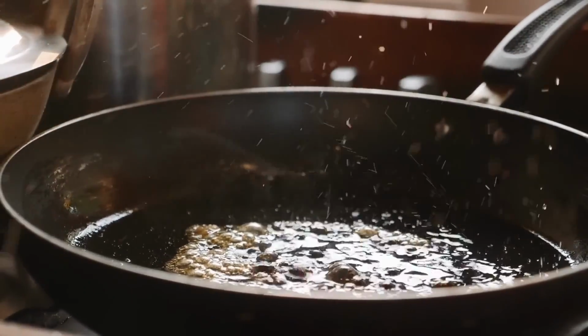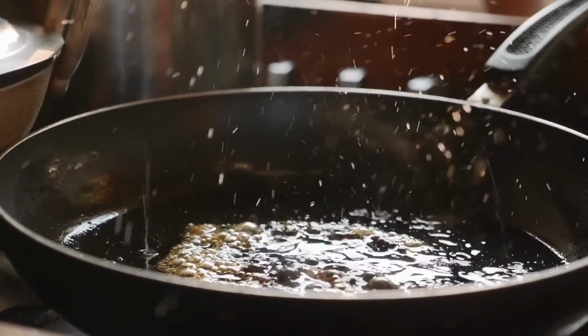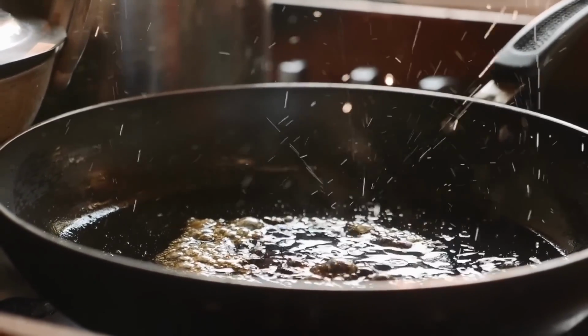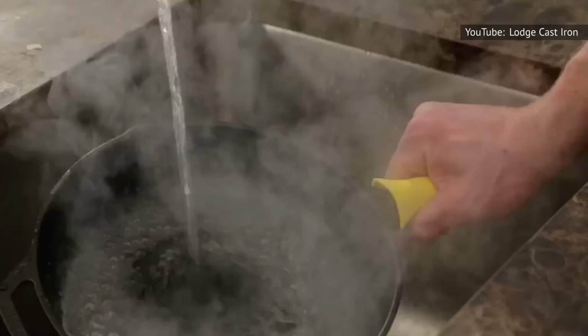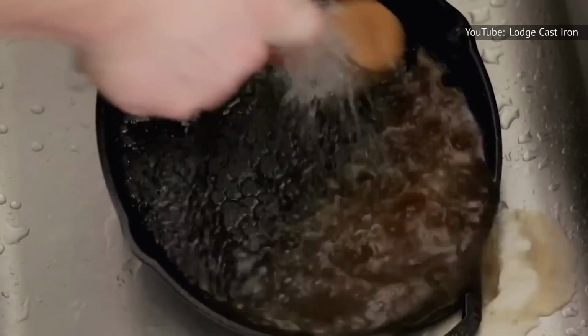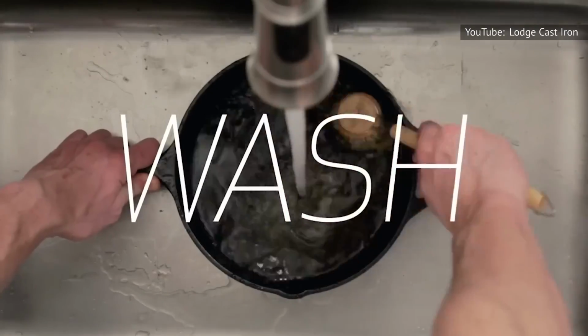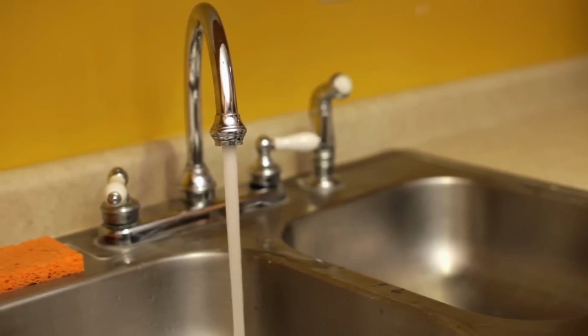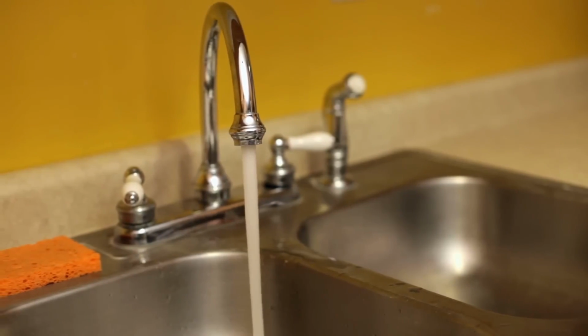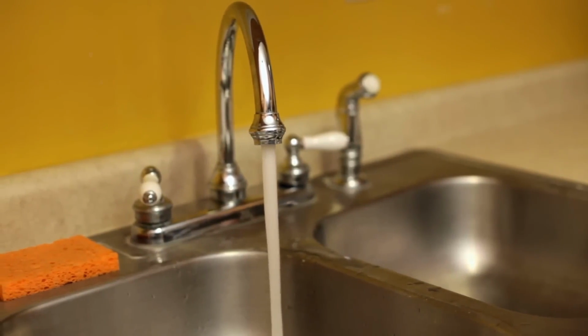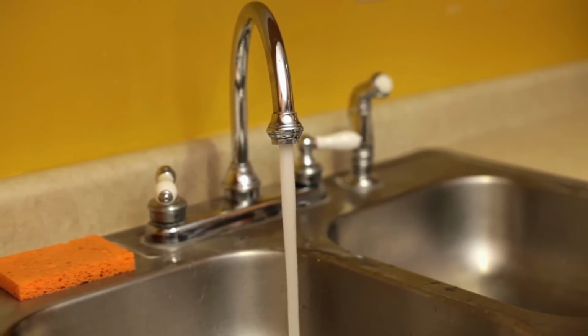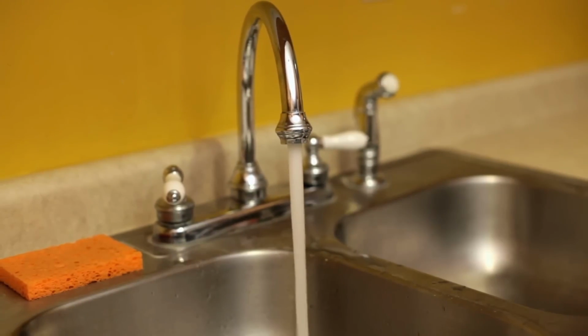Additionally, if the water is too cold when it hits the hot pan, you also risk causing thermal shock to the metal. Ultimately, this can lead to metal fatigue and cause the quality of the cast iron to crack and break. The best method to avoid both problems is to first let your cast iron cool down to, at most, a warm temperature. This way, you negate the risk of causing a grease splatter once you start cleaning. Then, be sure to let the water warm up before you use it to clean, in order to avoid thermal shock and potential damage to your pan.